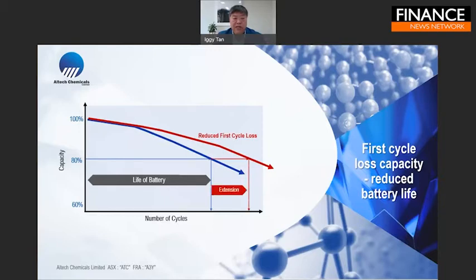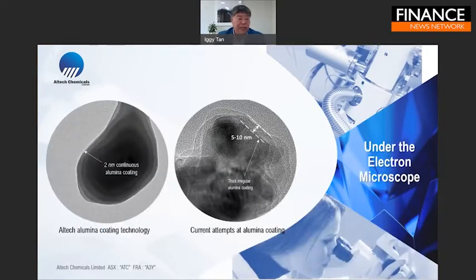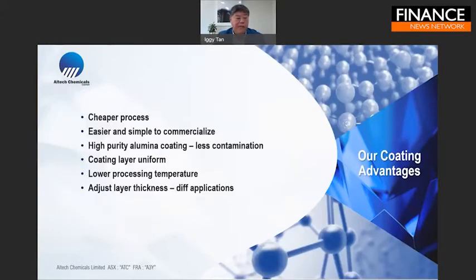When you have a reduced cycle loss capacity, you have an extension of battery life. This is what we've achieved in the laboratory today in our research and development laboratory. On the left-hand side, you've got a graphite particle with our very thin, continuous alumina coating. And on the right-hand side is typical of what the industry is trying to do, very irregular coatings and very thick coatings of alumina. So we believe that our process is a cheaper process. It's easier and simple to commercialize.